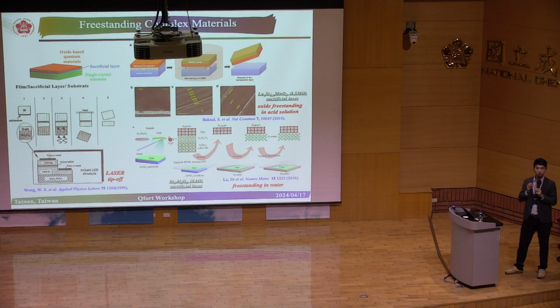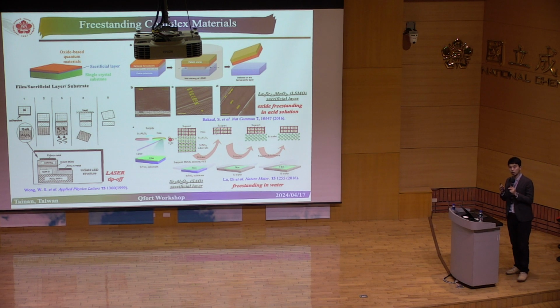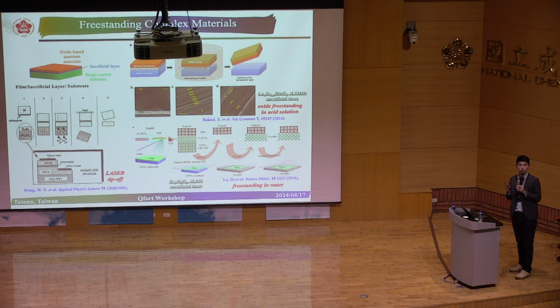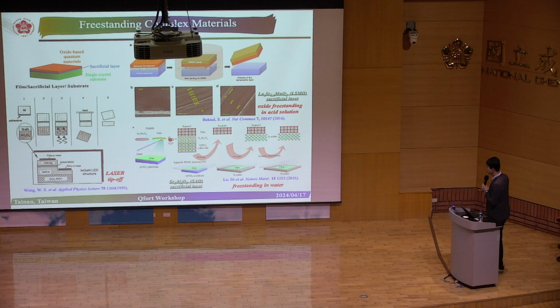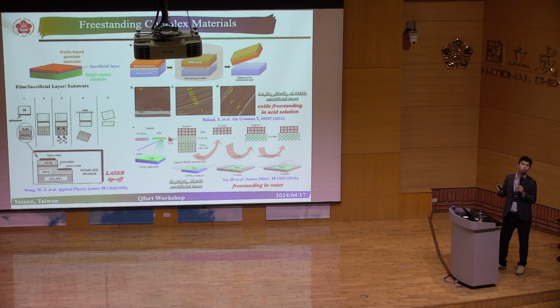You might wonder whether it is possible to do it in a neutral solution, simply because if you immerse your material in an acid solution, sometimes it will do some damage. In the same year, a team at Stanford, Harold Hwang's group, found strontium aluminate. This is a new material, and it can easily dissolve in water. So you use the same thing: you make the epitaxial materials, and you immerse them in water, and after probably 1 or 2 weeks, you can have the freestanding form.